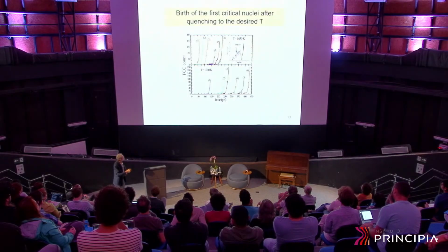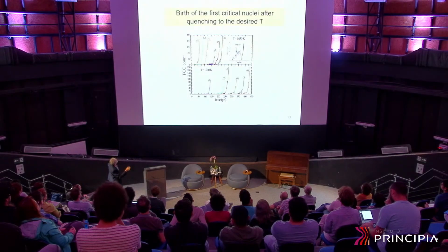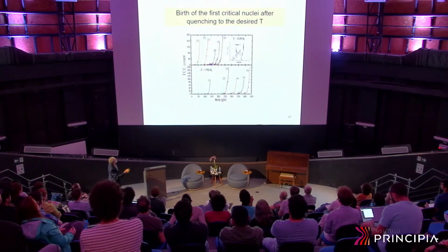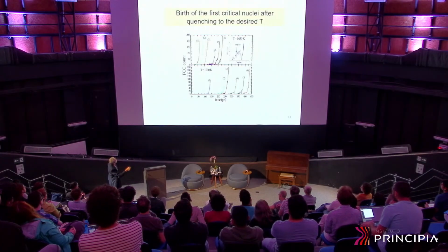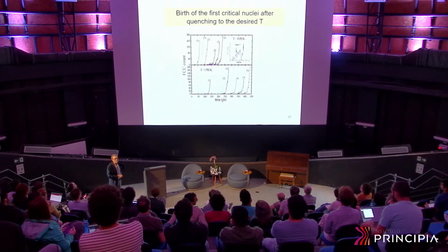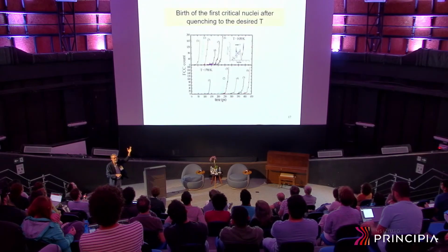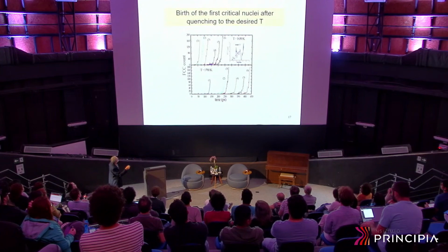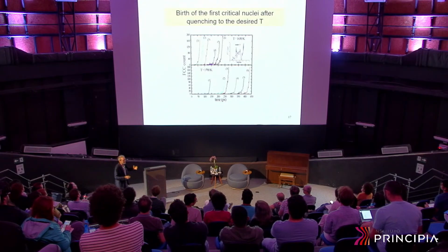So that's what can be done. You quench your liquid to a certain temperature, and you wait a little bit, the first nucleus has formed. Then you melt the whole thing again, and do another experiment, the first nucleus is formed. It's a stochastic process. You have to repeat this several times.